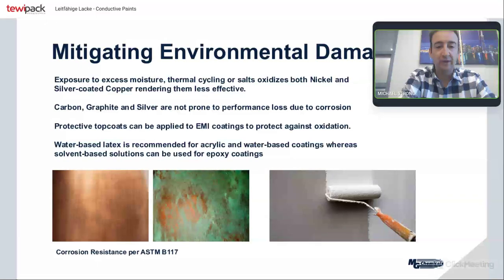With our acrylic and water-based series coatings, we recommend applying a water-based latex as a protective top coat. We don't recommend a solvent-based one because, again, that solvent can attack the underlying film and potentially put some holes in the conductive film where radiation can leak in and leak out, so it could compromise your film. Whereas with the epoxy coatings, once they're cured, they're quite chemical resistant, so you can basically use whatever you want and not have to worry about the conductive coat being compromised.